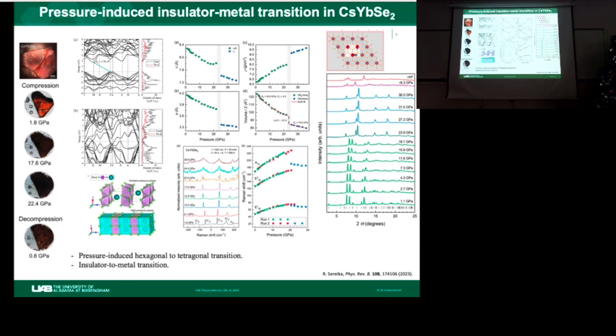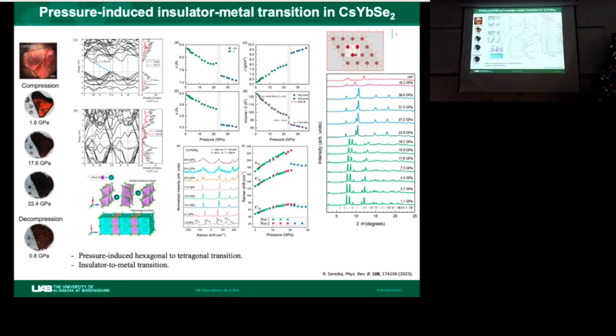Okay, here is another example. It's a lot of data, but you could just ignore these details. This is an example of pressure-induced insulator-metal transition in a so-called quantum spin liquid material. I'm not going to go into detail about the physics of this material. I just want to show you that at ambient pressure, before compression, this material is an insulator with an indirect gap of about 1.76 electron volt, and as you compress it, the color becomes dark, and we all know the color is a reflection of the band gap, so under pressure the band gap is closing. What we found was there is a crystal structure transition with a very large volume collapse, and that's causing this closing of the indirect band gap. This finding is also confirmed with Raman scattering data.